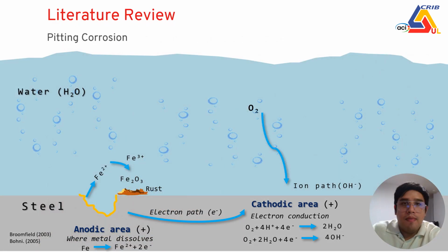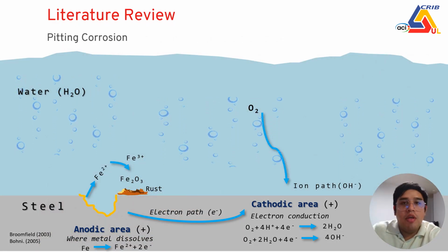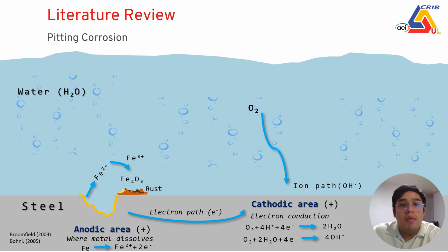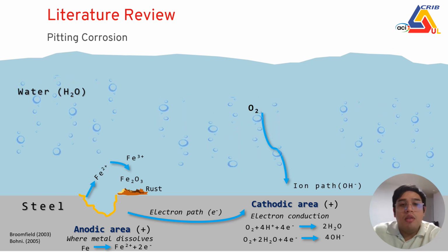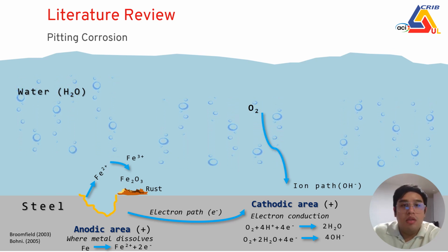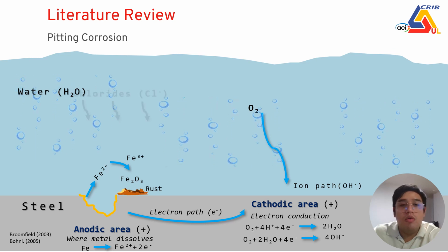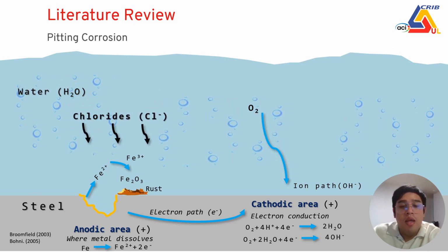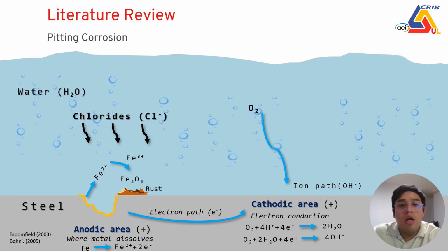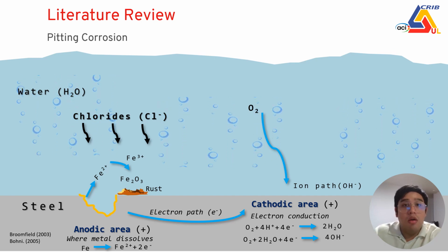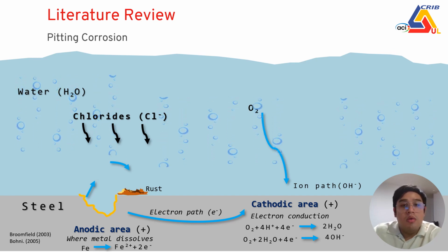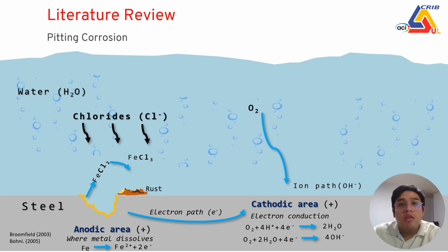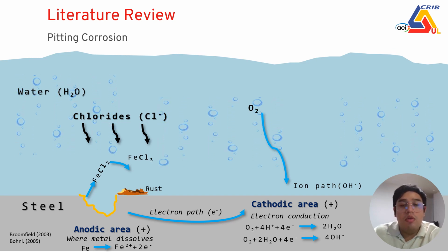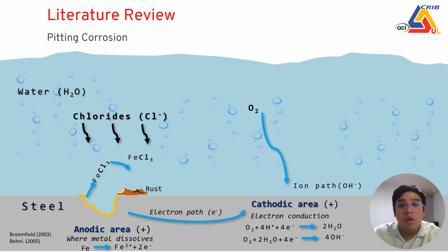So a particular case grabbed my attention because there is something that we call pitting corrosion. And this pitting corrosion happens when chlorides arrive to the system. This chloride will attach to the iron that is being oxidized. So this will create new products, and these products will be released to the pore solution.